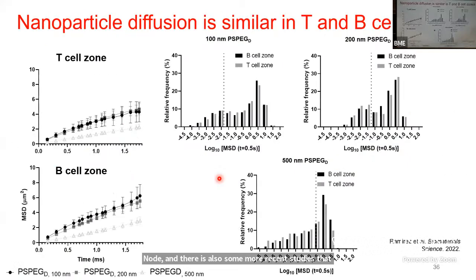And we can quantify this further and actually look at the distribution. So for 100 nanometer particles, the B and the T cell zone, really it was very similar across the board, actually 100, 200, 500 nanometer particles. So all of them were diffusing quite well throughout the lymph node. Now we can use this information and that mean squared displacement to extrapolate the pore size also of the region.